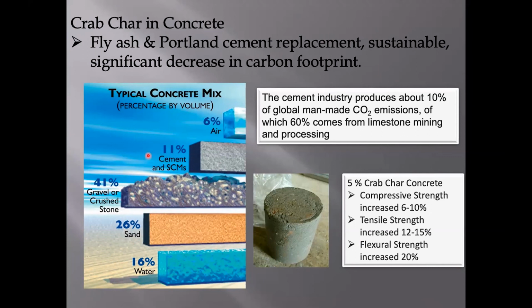And that limestone mining process is really energy intensive and actually makes up about 10% of global man-made CO2 emissions. And so the cement is made by heating the limestone that is mined in the quarry at about 1500 degrees Celsius with other components of the cement in a kiln, and that generates the calcium oxide that is required for the chemical composition of cement.